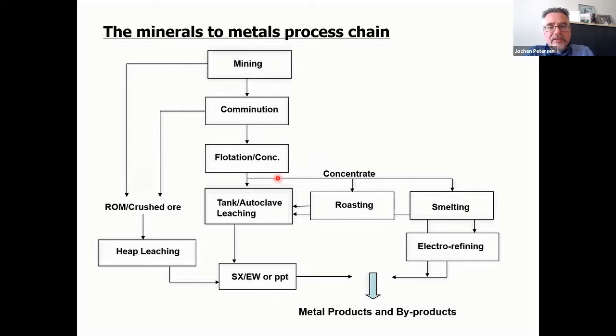So the concentrate can either go directly into a hydrometallurgical process, which are so-called leaching processes that take place in tanks or under pressure in autoclaves, or the concentrate goes into a roasting process where the material is either oxidized or reduced at high temperatures, and the calcine or the reduction product is then put again into a hydrometallurgical process where it's leached and dissolved. So what you're doing in roasting is really rendering the mineral phase of your target metal in the ore into a form that makes it soluble in aqueous solution.